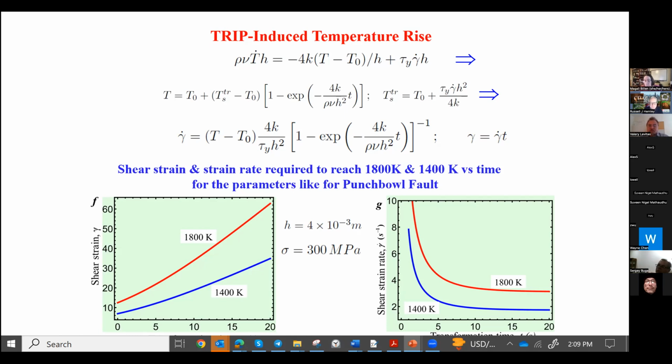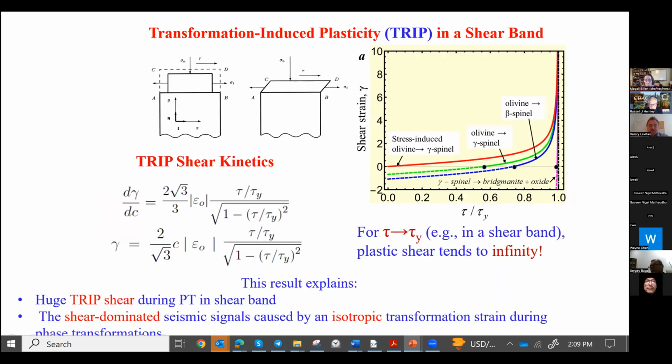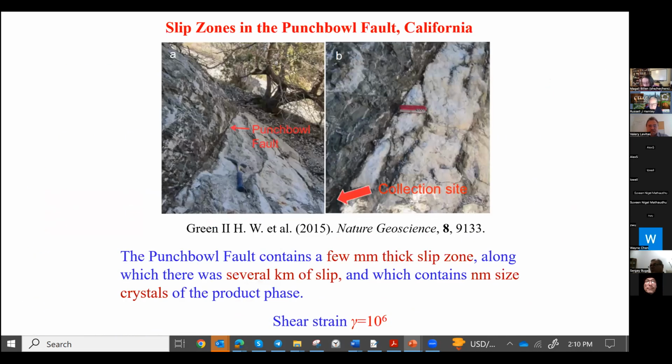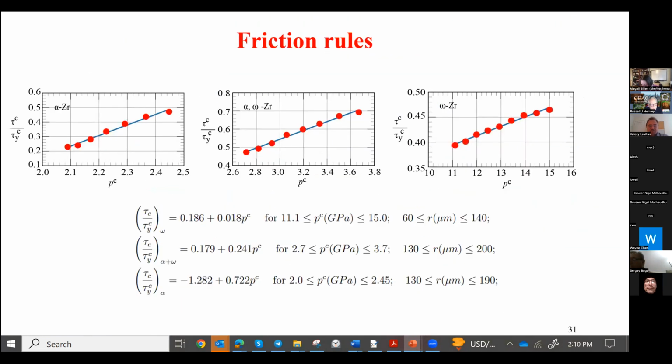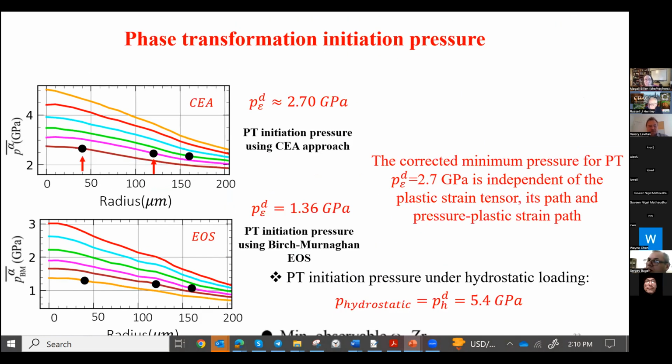Yes, we found amorphization in silicon carbide. It was a while ago. Let me see. For silicon, there was amorphization for 30 nanometer particles, even under hydrostatic loading and unloading. And this is slow unloading. And I believe that, well, I know a lot of data that, for example, nanocrystalline nickel titanium under severe plastic deformation undergoes amorphization.